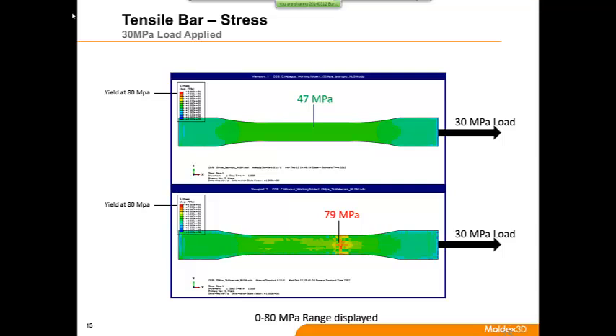So back to the tensile testing. You can see without considering the fiber orientation, which is shown on the top, the stress distribution is uniform. There's no stress concentrated region. But in reality, there's a weld line in the center, so you can see there's a really high concentrated area showing an 80 megapascal stress over that region. So we can say that without considering this kind of anisotropy, you will have limitations getting your structural simulation correct.